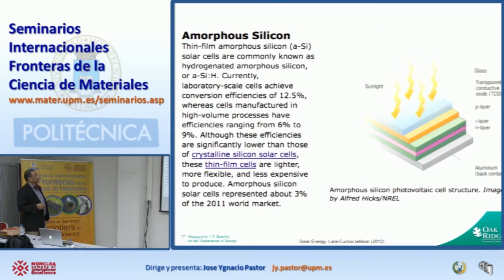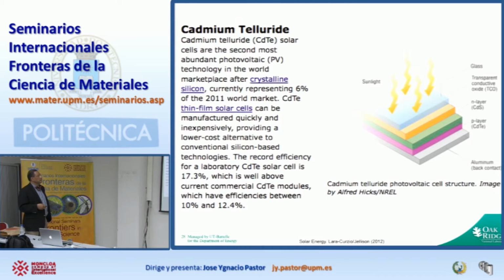silicon cell. Same thing with amorphous silicon. They are less expensive. The efficiency is not as good. It's only 12%, but the cost of this is much lower. Cadmium telluride. One of the concerns with cadmium is that cadmium is a fairly toxic element. So people are very afraid of using cadmium. And there are concerns about the availability of tellurium.